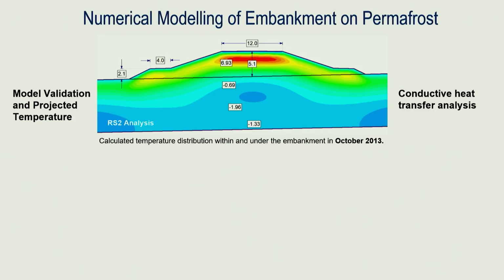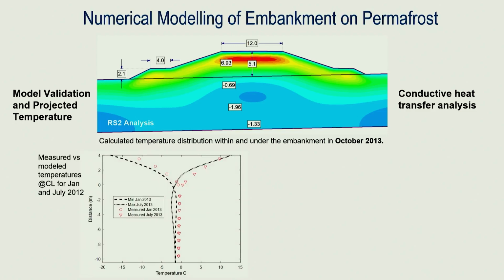This is a sample of the basic conductive heat transfer analysis. I'm not talking about anything complicated here. It's a very simple heat conduction analysis. And this is basically the results obtained using the software in October 2013. That's comparing calculation versus measured. And what you see here is the distribution with depth at the center of the embankments. So these lines represent the calculated response, or distribution of temperatures. And these triangles and circles represent the measured values.